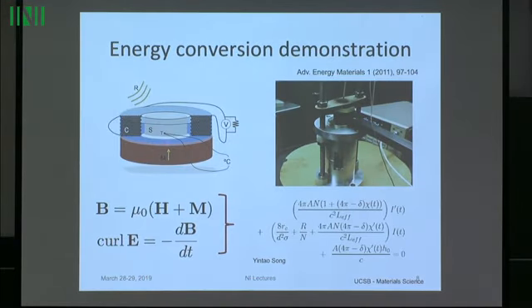So the basic idea, and we'll go into a bit more detail in a few minutes, is to recall the dipolar relation. We derived that last time. Remember, that came from taking the dipole field. From a mathematical point of view, it's singular integrals. Taking the dipole field, cutting out a little region around the dipole and removing the singularity. So you smooth the field on a small neighborhood of the singularity of the dipole, and you do it in a divergence-free way, and then you homogenize, and that gives you the B field, and M is the magnetization, the dipole strength per volume. If you homogenize that, you get this relation, which is fundamental to dipolar magnetic materials or dipolar ferroelectric materials, as Peter was also saying yesterday. It doesn't have any material constants in it.